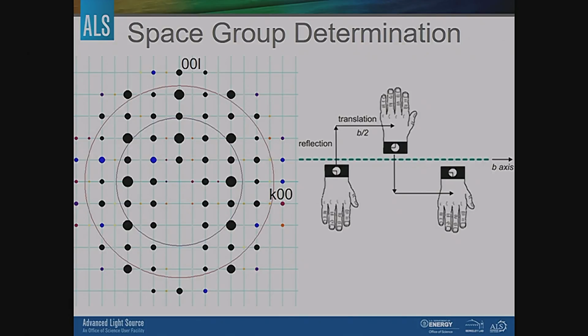Yeah, so you can see that there is a weakness when that should be H, but there's a K there. So if we're H, this is the H0L plane, and we have absences here when H is odd. And so we don't have anything in the L direction, because all the L direction reflections are present. So this weakness in the H direction is due to a glide plane, because you have this translation every half, and you actually produce this weakness. So it's almost like a halving of the unit cell, but that's only an interference effect.